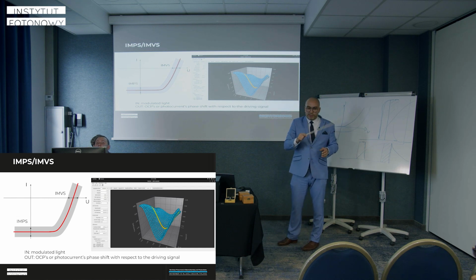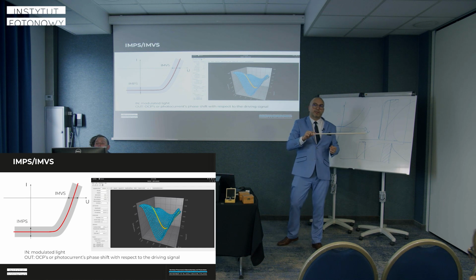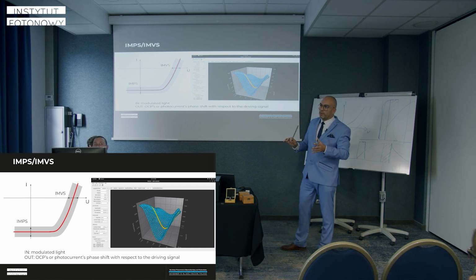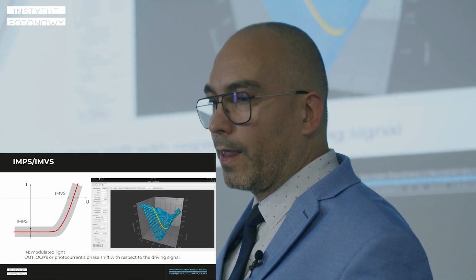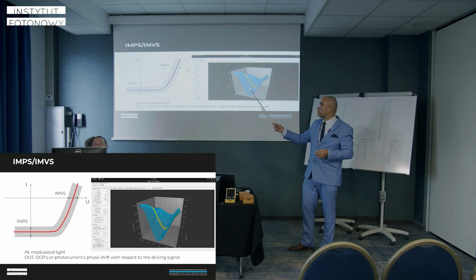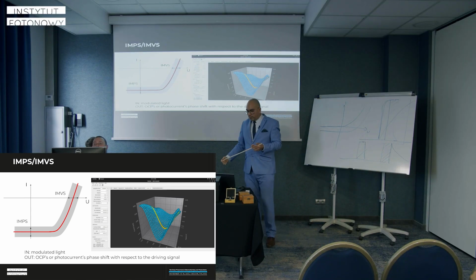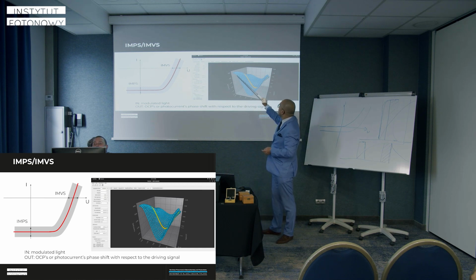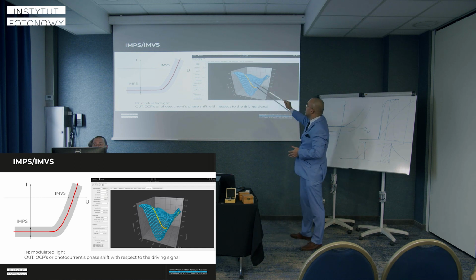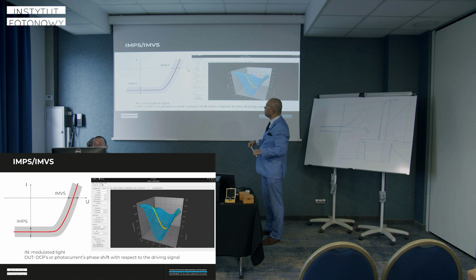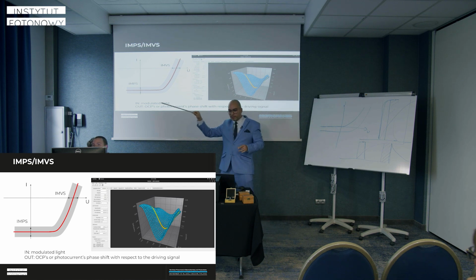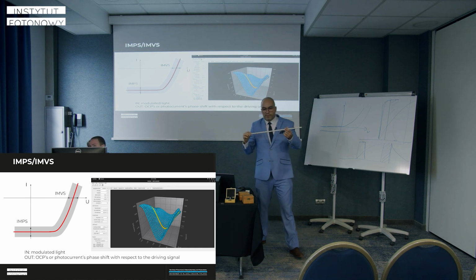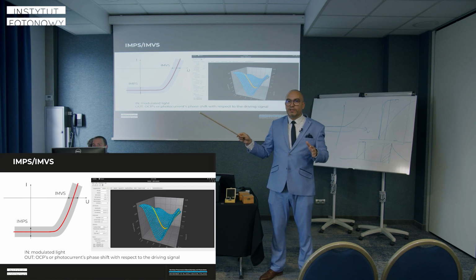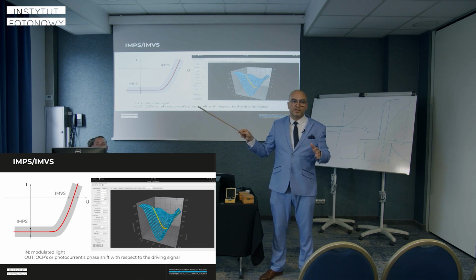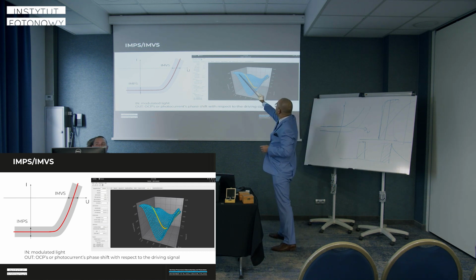If we apply a low frequency of light, comparable with the time constant that depends on the capacitance of the sample, we can see that the photocurrent values just follow the changes. And the faster the light modulation is, if there are some frequencies that are too fast, the changes are too fast for our sample, and then we observe just shifting of the phase and decreasing of the amplitude.